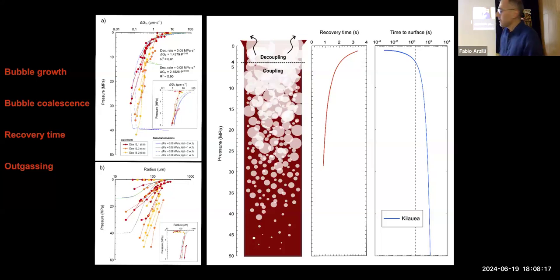So I think this is the last slide. We were able to measure bubble growth, bubble coalescence, recovery time, and where a permeability network can be promoted, and the outgassing. And we observed during our experiments that up to basically 4 megapascal, the system was completely closed, and despite coalescence, the coalescence is so fast that permeability is not developed, and you have a coupled system, so your gas is coupled with the magma.